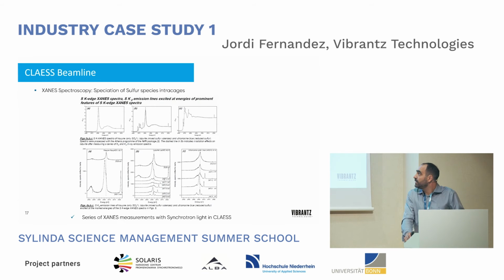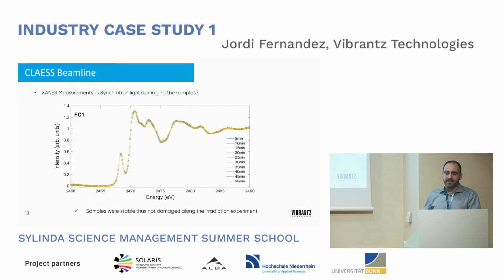Then at CLAESS, what we do is X-ray absorption spectroscopy to do the speciation of the sulfur species in the ultramarines. When we contacted ALBA, they recommended we run these experiments because it was the only way to determine this speciation of the sulfur. I think it was the first time that they were doing this kind of experiment, so we were like the first test. The first thing we did was study how our samples behave in this technique. We ran several experiments to see if the samples are stable enough to do this speciation, and the answer finally was yes. The ultramarines were stable under this kind of radiation, so we could continue to the next step.